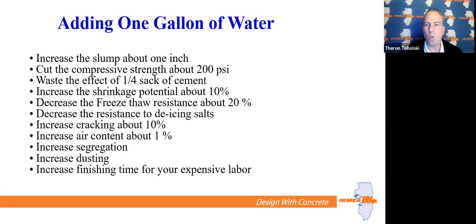Think about how many gallons of water can be added to a truck on site. There could be 30, 40, 50 gallons of water on some projects. So it really has a major effect. It decreases the freeze-thaw resistance by 20%. It decreases the resistance to de-icing salts. It increases cracking by 10%, right? Nobody wants a cracked concrete pavement. That happens, but we don't want it. So again, 1 gallon of water increases cracking by 10%.